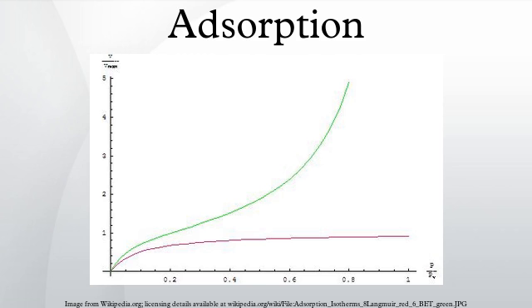Kisliuk. In other instances, molecular interactions between gas molecules previously adsorbed on a solid surface form significant interactions with gas molecules in the gaseous phase. Hence, adsorption of gas molecules to the surface is more likely to occur around gas molecules that are already present on the solid surface, rendering the Langmuir adsorption isotherm ineffective for the purposes of modeling. This effect was studied in a system where nitrogen was the adsorbate and tungsten was the adsorbent by Paul Kisliuk in 1957. To compensate for the increased probability of adsorption occurring around molecules present on the substrate surface, Kisliuk developed